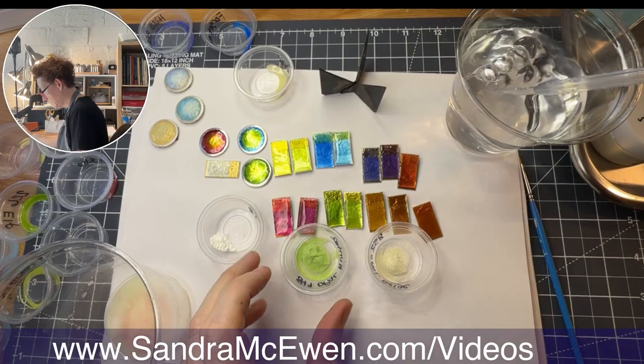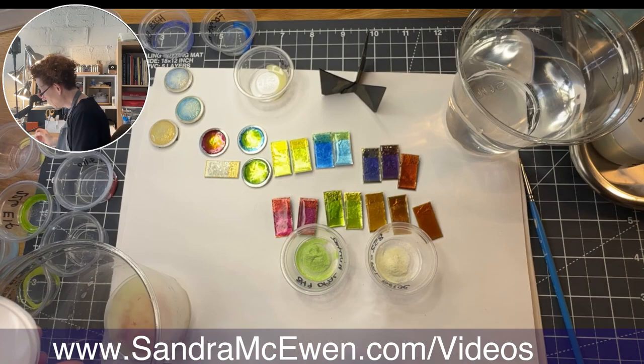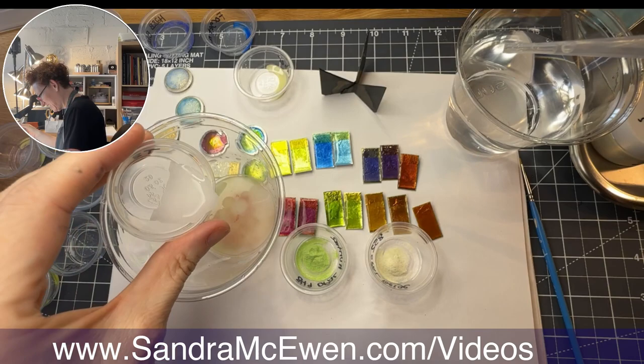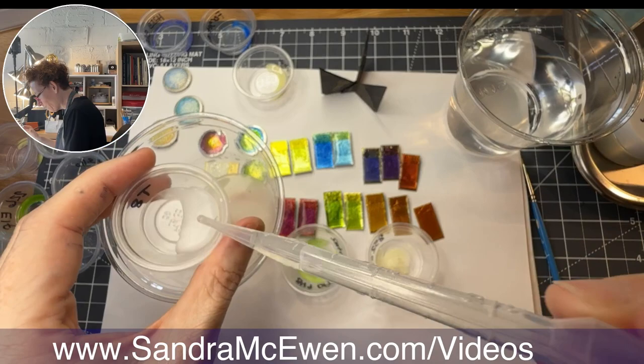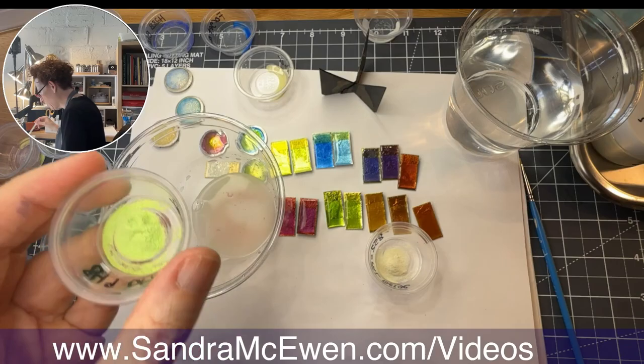We're going to start with the T8. Normally, especially if you're going over a white, I would not do a ton of washing, but you can wash away the opalescence, so I really don't want to do that. I'm just going to do a little mini wash. It's so finely ground, this T8, that I might be pouring more of it away than I'm keeping in the washing. And then this, just a little bit.